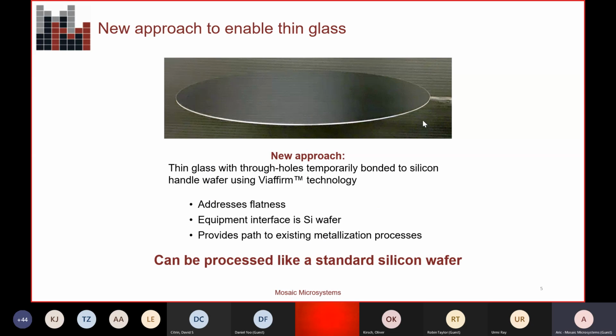And so what Mosaic is doing, and this is our core technology, is we have a temporary bonding technology where we could take a glass or a silicon handle, but primarily we'll use a silicon handle wafer, and apply a very thin layer that we call ViaFirm. So it's the ViaFirm bonding technology. You apply that to the handle, and then you bond the thin glass to the silicon handle wafer. It's a submicron layer, and it's very clean and very uniform, and it's a room temperature bond.